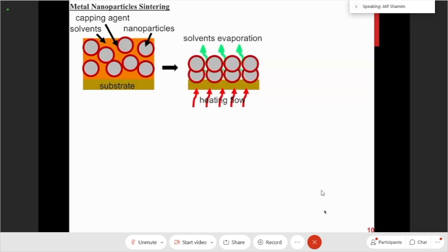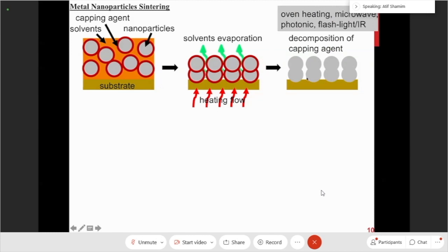So what you do is that there are a number of ways. You could simply heat them so that the solvent evaporates, and the ligands melt away. The polymer coatings melt away, and you're just left with these nanoparticles which can mix with each other or connect to each other. This process of getting rid of the solvents and getting rid of these polymers, traditionally it is called sintering. Right, sintering. So sintering can be done a number of ways. It could be simple in an oven, and there are many other methods which I'm going to show you in this presentation.